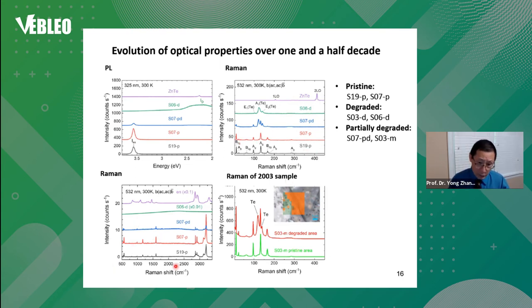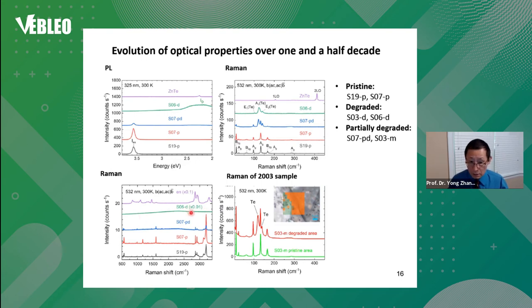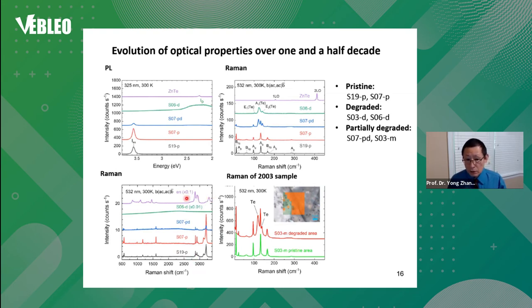In the higher wavenumber regime, these modes are mostly related to the organic molecule. Again, the pristine samples show almost identical sharp transitions, while the partially degraded sample shows weakened peaks, and the severely degraded one shows no molecular Raman modes at all. For comparison, an ethylenediamine solution shows almost similar Raman modes as in the crystal, but they are much broadened — because in solution the molecules are randomly oriented, while in the crystal they are all locked into a well-defined position.